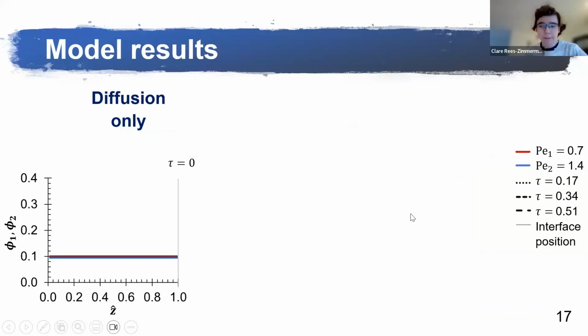On this slide are some example model results. So firstly, the diffusion-only model. On the y-axis is the volume fraction of each particle type. And on the x-axis is the scaled height up the film. So the top surface is the right-hand side of the graph. That's the gray line showing the solvent-air interface. At time 0, the concentration profiles for each component are flat. We're starting off with a homogeneous mixture. In red, I show the small particles, and in blue, I show the large particles. These are example results for Peclet numbers straddling 1. So in these examples, diffusion and evaporation are roughly similarly important.